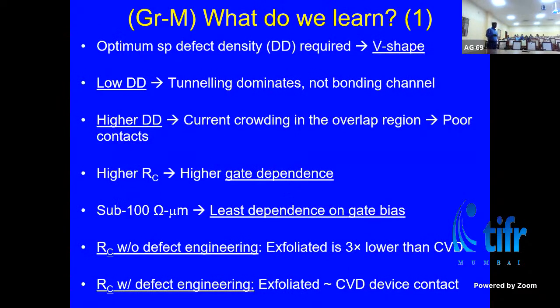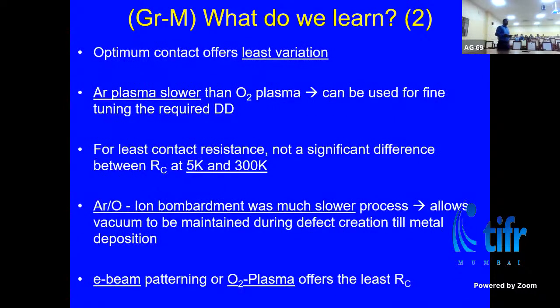So at sub-100 ohm-micrometer, there is the least gate bias dependence. And when you don't have this defect engineering, the exfoliated material was 3 times lower in contact resistance than CVD. So the contacts are also a function of the quality of the material, exfoliated versus CVD. But when you have the defect engineering, the exfoliated and CVD contact resistances are pretty much the same. And of course, I talked about the oxygen plasma.